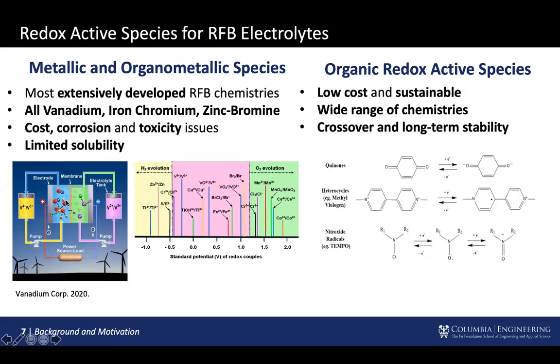So if we think about this, what this means is essentially you can only really dissolve so much of, say, a metal-based salt in water or another electrolyte before it crashes out. And if we think back to the previous slide I have, that just sets a limit to the achievable energy densities. So those are kind of the challenges of metallic species, and these prompted research in the area of organic